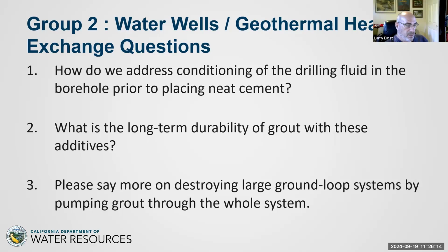One thing to consider also is that as you start getting 60 to 70 viscosity, they're not circulating that in this particular case. So the plastic viscosity sets up and this becomes almost a pudding in the well if it's not conditioned. If you look at the rheology of it, viscosity is related to time, and after a while, if it's really poorly conditioned fluid, the plastic viscosity gets to the point where it is essentially a pudding or a paste. Yep. And so this is why it's an issue. It isn't necessarily the weight or the viscosity at the exact time. It's also what happens over the duration.